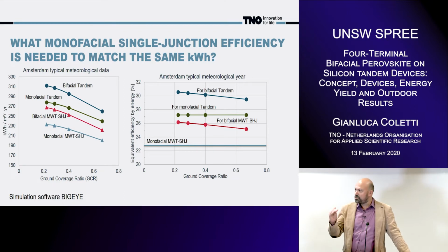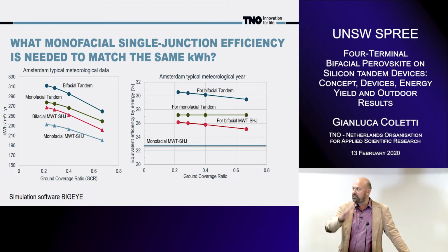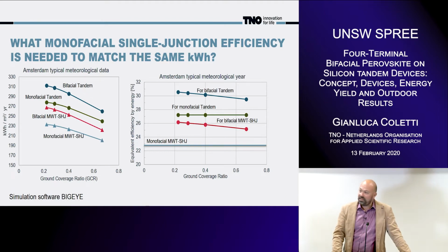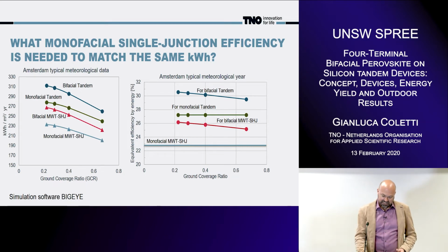Now, this is the first, let's say, indication. A monofacial device, single junction, over 30% is physically not possible. This is just a quick note. And that means that when you want tandem, you need to target at least this 30%, because then you will be above what you can do with the bifacial. So it's, let's say, the entry level.